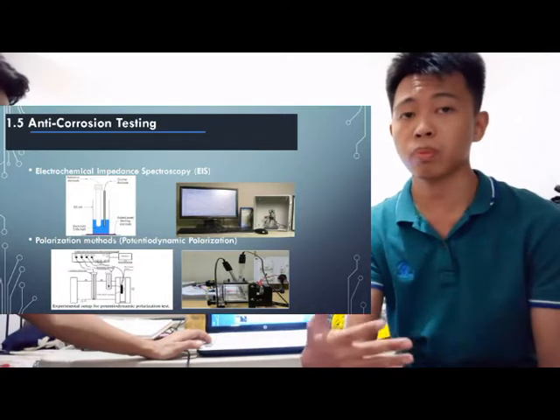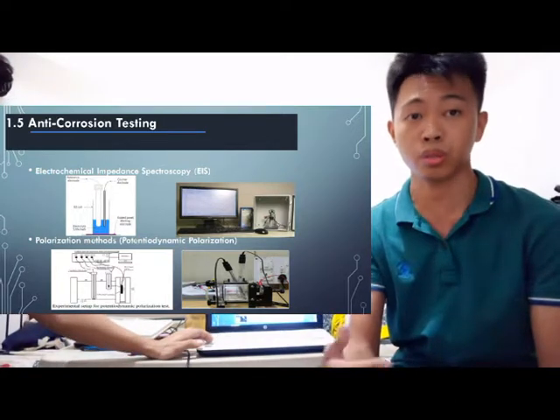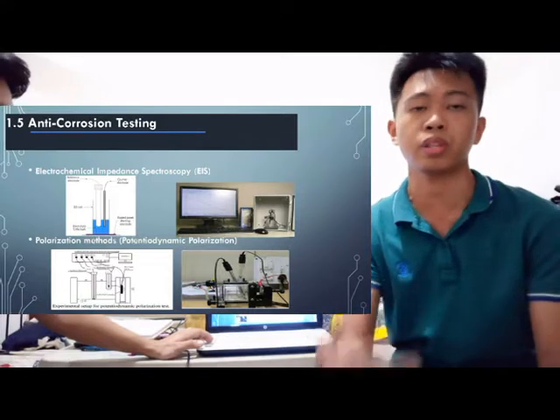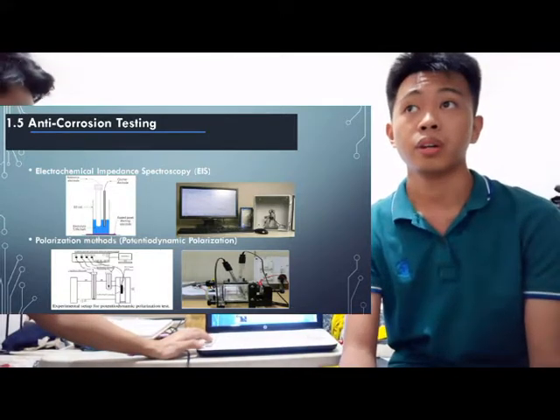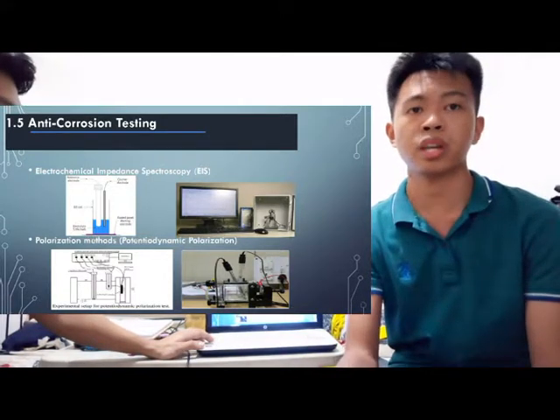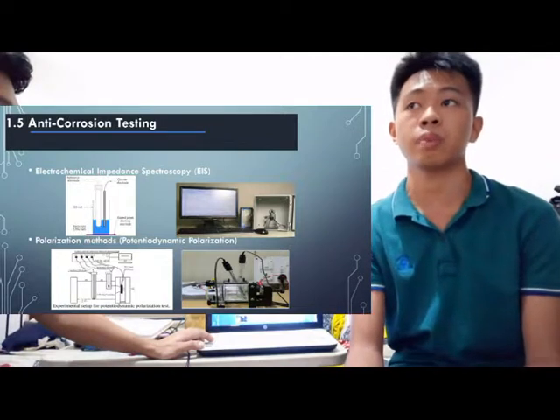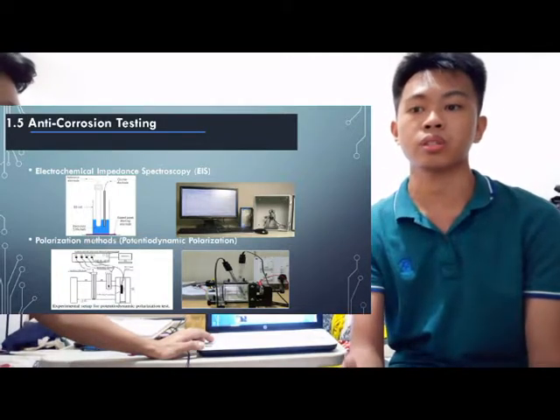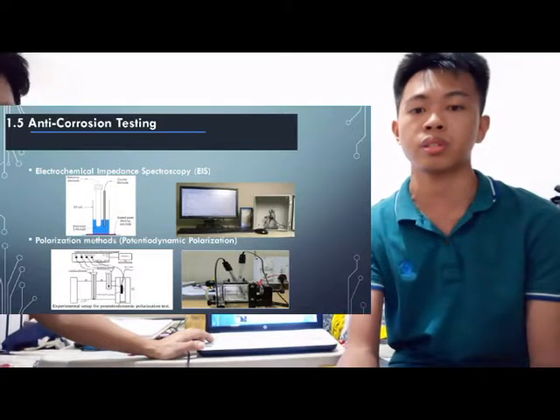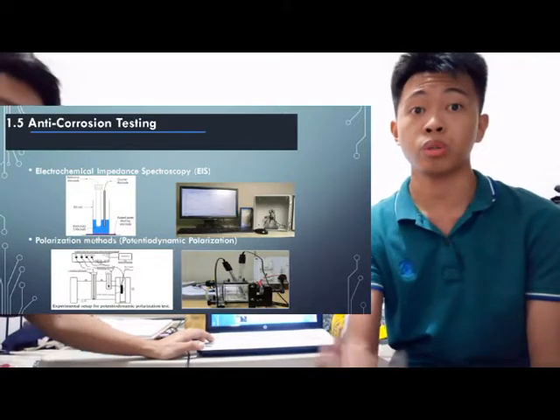The most common polarization method used by many researchers is the potentiodynamic. For our study, we use the potentiodynamic polarization method because it provides parameters such as corrosion current resistance and the corrosion rate. So for the characterization of our coating,